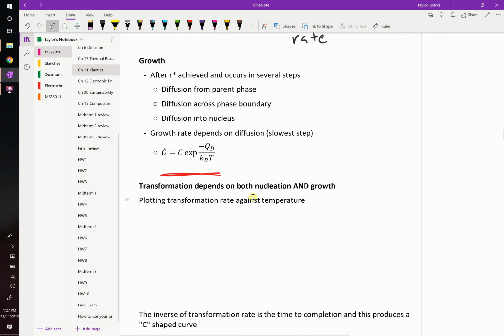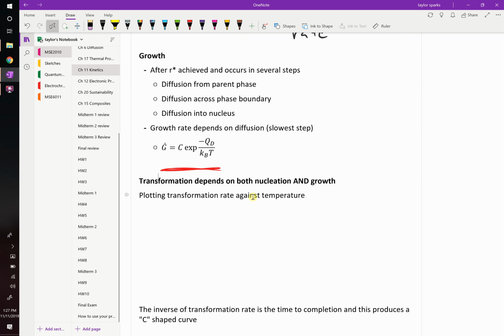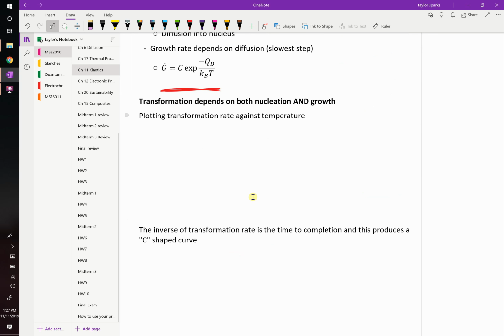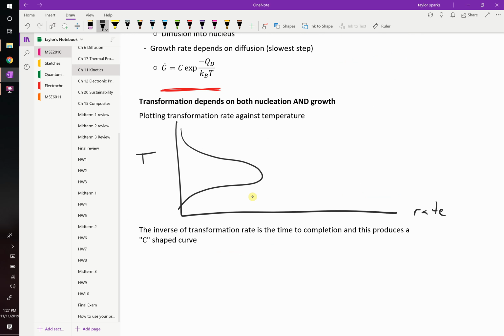Okay? Any questions? Okay. So remember that your total transformation doesn't depend on just nucleation, but rather it depends on nucleation and growth. So if we were to plot this one more time, the total rate on the x-axis versus temperature, we know that nucleation looks something like this, but growth looks something like that. And your overall transformation is going to multiply those two curves together. Anytime you take two exponentials and you multiply them, you get something that kind of looks like that. So that's going to be your overall, I'm going to put T dot, transformation rate.